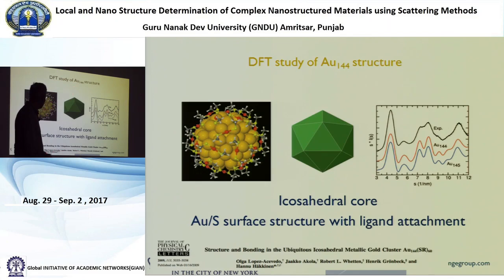And so Hannu Häkkinen, who's a Finnish physicist, did a DFT prediction of what the structure of this is, and it was a heroic effort because he actually did the calculation with the cluster covered by these organic ligands. So he had 144 gold atoms, he had 60 sulfur atoms, and he had almost an equal number of carbon atoms for the ligands. So it became a very large DFT calculation. But he succeeded, and he predicted that the core of this gold cluster would have this icosahedral shape. So icosahedral is a shape that doesn't fill space. There are no crystal structures with this shape. But it's a very stable cluster for a finite cluster. So he predicted this icosahedral core.